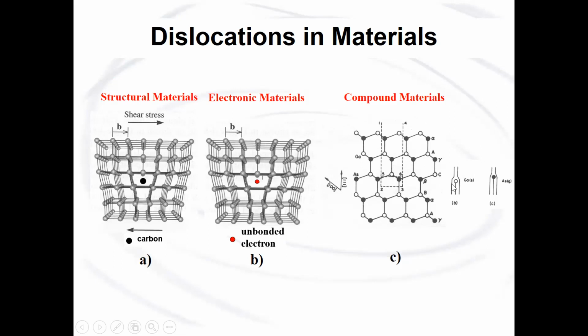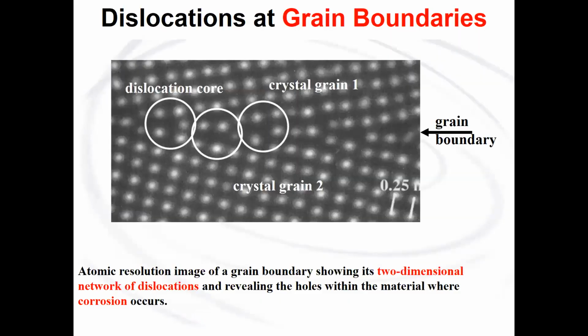They can be terminated by gallium or arsenic. With gallium, there'll be an extra positive charge. With arsenic, there'll be an extra electron, and these will annihilate any kind of charges within the material to stop the generation of photons. At grain boundaries, the misfit between the two adjoining grains is accommodated by dislocations. You can see those nicely here, and they form a two-dimensional network, and they are essentially where corrosion occurs inside materials.